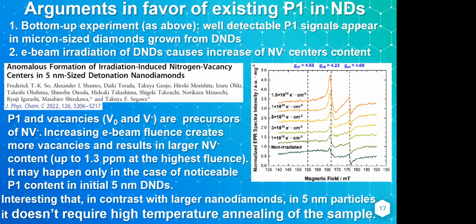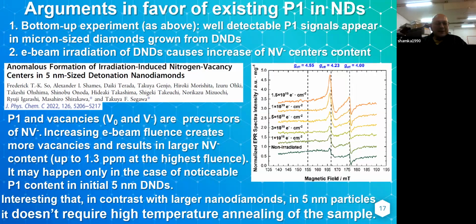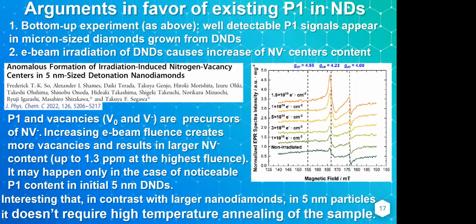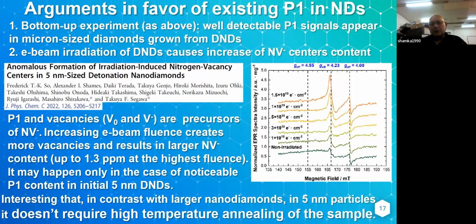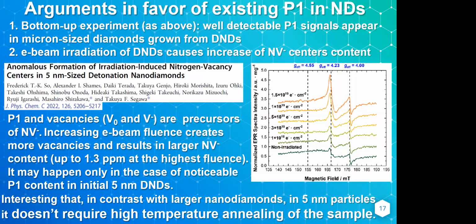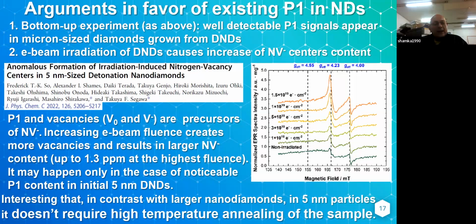And well, how about not such drastic conditions? For example, you can eliminate all those dangling bonds by, for example, reducing them chemically, right? Without changing the nanodiamond size. Okay, this is a good question, and I would like to see this experiment with quenching of dangling bonds. In fact, when you quench dangling bonds, you have to recreate the hyperfine structure in the EPR spectra. That's what I was thinking of, yeah. And then there is no need to increase the nanoparticle size. I am sure that it should be so, but the main question is, how can you do it?